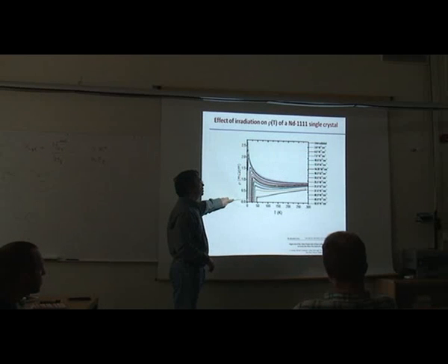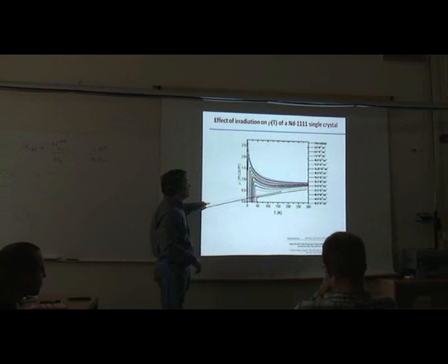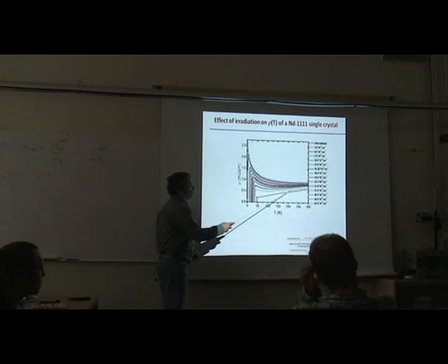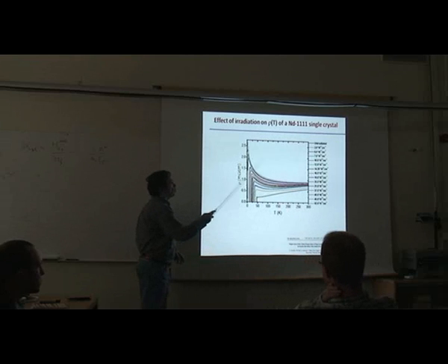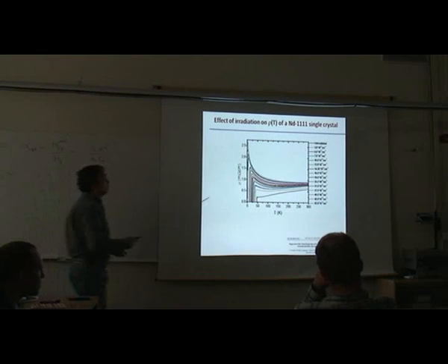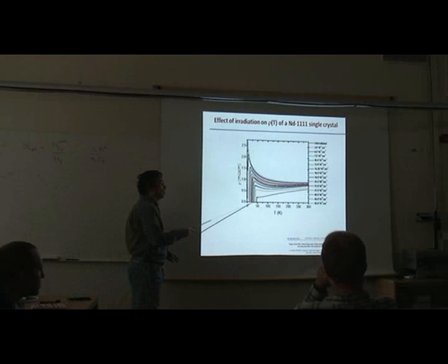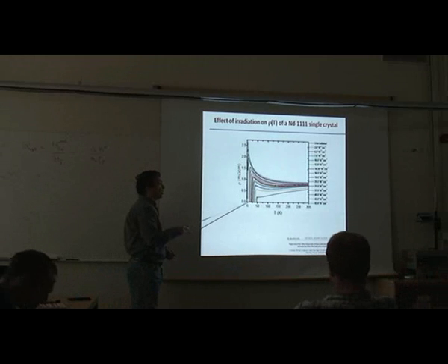This is resistivity as a function of temperature. The black one shows the unirradiated sample. So as we irradiate, the resistivity goes up, and also this strong upturn develops. Really, the effect is quite significant because the difference between this point and this point is a factor of 3. It's not a small effect. And then you can see that TC decreases. TC is this point. So as we irradiate, TC goes down and finally it becomes 0.